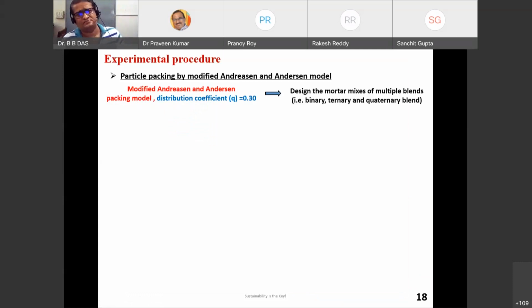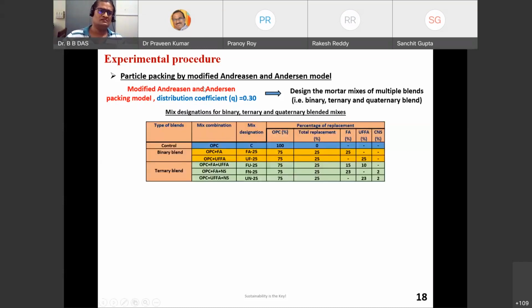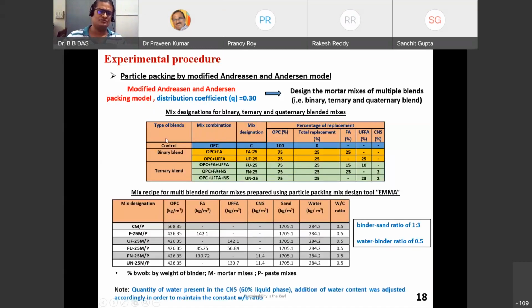Then the experimental procedure: we adapted particle packing by the modified Andreasen and Andersen model. We designed the mix proportions for the mortar mixes and the cement paste. As I was telling you, the mix recipe of the multi-blended mortar mix is prepared using a particle packing design tool, and that is nothing but EMMA. It is software which works on the principle of the modified Andreasen and Andersen model.